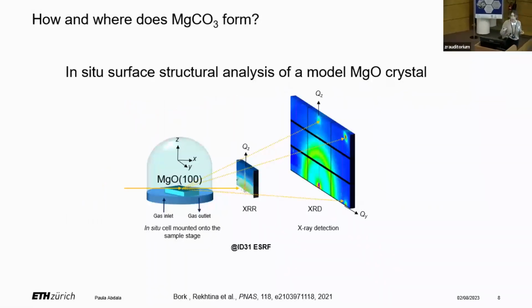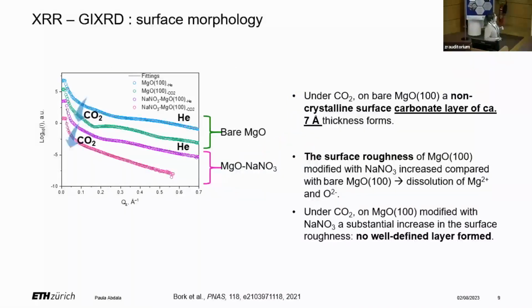So we wanted to address this question, and our approach was to understand how and where magnesium carbonate forms, using a model system, a magnesium oxide (100) crystal. We investigated the surface of this crystal under reaction conditions. This was done at ID31, and we investigated it by X-ray diffraction and X-ray reflectometry.